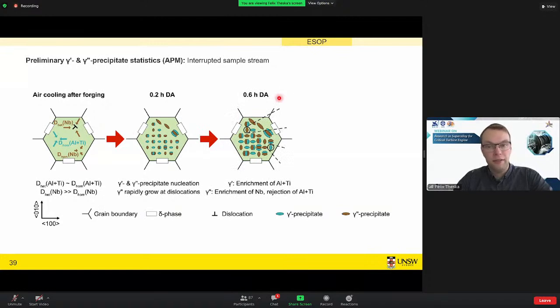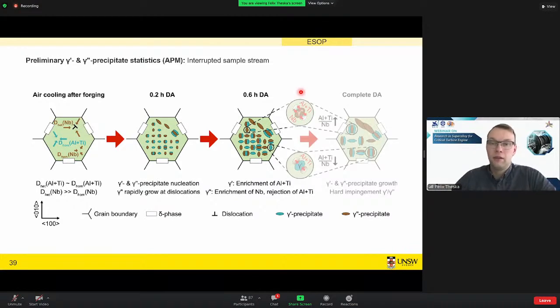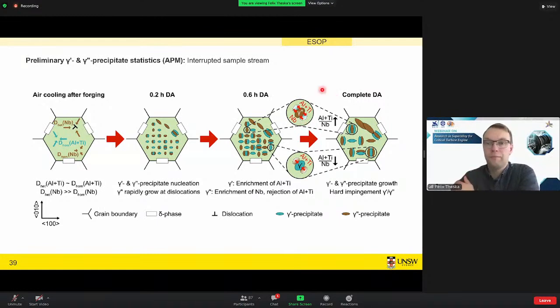After 36 minutes of aging, all populations start growing, and during the time of 0.6 hours direct aging until the final aging step, we observe this formation of co-precipitates. If we consider the change of the chemistry, we see that gamma double prime takes niobium from the matrix, but gives back aluminum and titanium. And this favors the precipitation of gamma prime on the interface of the gamma double prime particles. Whereas for the gamma prime particles down here, we have the opposite case. So aluminum and titanium are taken from the matrix, which favors the precipitation of gamma double prime, so that in the final microstructure we end up with these co-precipitates.